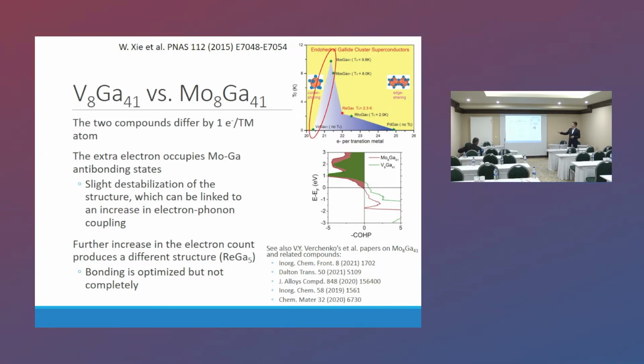endohedral clusters case. V8Ga41 versus Mo8Ga41. Both very complicated structures. One is not superconducting down to well below 2 Kelvin. The other one has a Tc of almost 10. Great. So they only differ by just one electron per transition metal. And the structures are the same, the connectivity is the same. So the extra electron is occupying the antibonding state. Sorry for the figure, I thought it was going to be bigger, but effectively there is a small number of antibonding states at the Fermi level, which increase the electron-phonon coupling and make them superconducting. If you increase the electron count even further by replacing molybdenum with rhenium, the structure would change. The crystal structure would rearrange to optimize bonding, but not completely, so it's still also a superconductor.